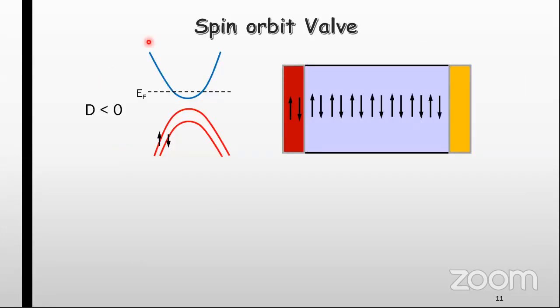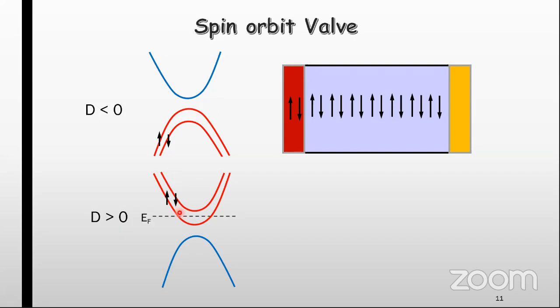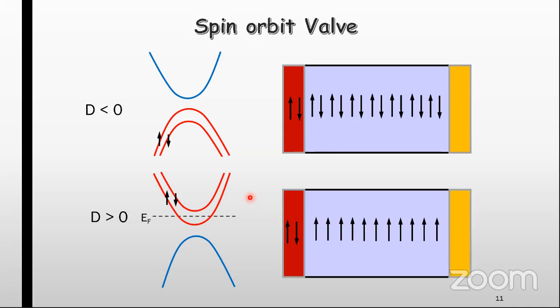So let's say we have this kind of band structure where the Fermi energy is lying in the conduction band and it is in an unsplit state. If we keep the Fermi energy fixed and flip the direction of the external electric field, we will get a split band. So it can act like a switch where, using the external electric field, we can switch on or off the spin orbit coupling in the system. There is also one more interesting thing: if we can somehow keep the Fermi energy in between these two band edges, then we can do spin filtered transport.